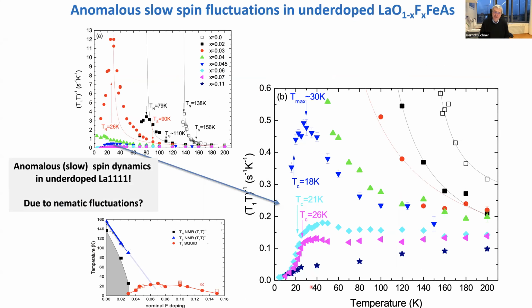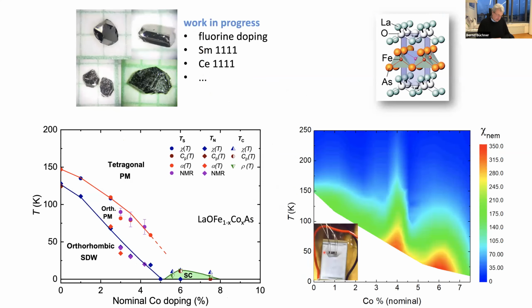Okay, these similar things you can also observe in these fluorine doped compounds. This we did earlier already, that you also have this very funny, very unusual slow spin fluctuations. And I think now it's becoming clear that this is definitely connected also to these nematic fluctuations, which are very soft in these optimally doped compounds. And only if you go to overdoped compounds, you end up with something which looks more or less like a usual metal. Okay, that is the first part.